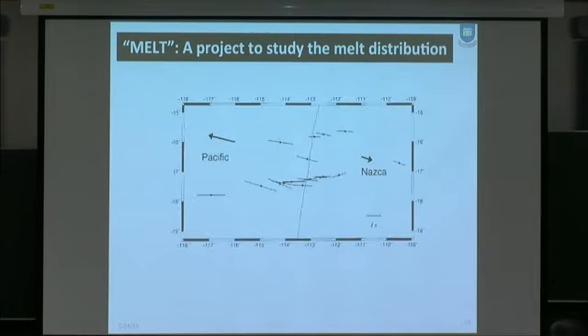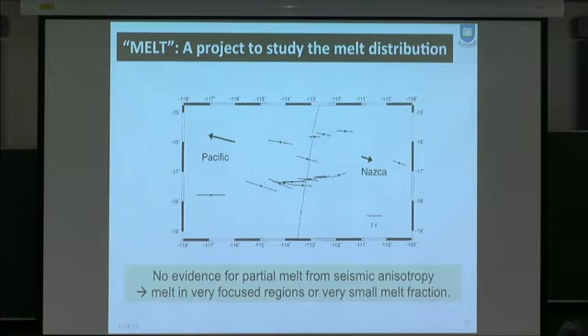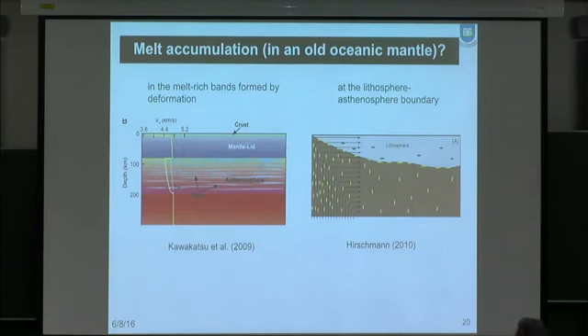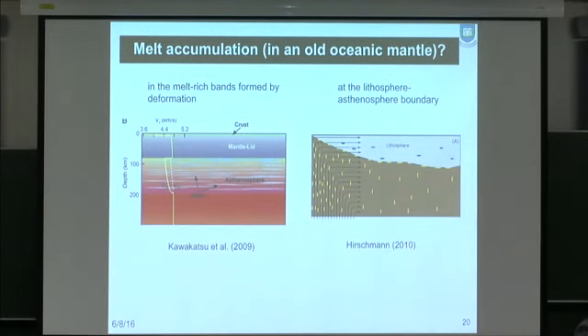Then what they found was, indeed, in the majority of cases, the fast shear wave direction is normal to the ridge, which is evidence against the presence of a large amount of melt causing the seismic anisotropy. So either melt is located in very focused, narrow regions, or the amount of melt is very small. So this is one observation against partial melt.